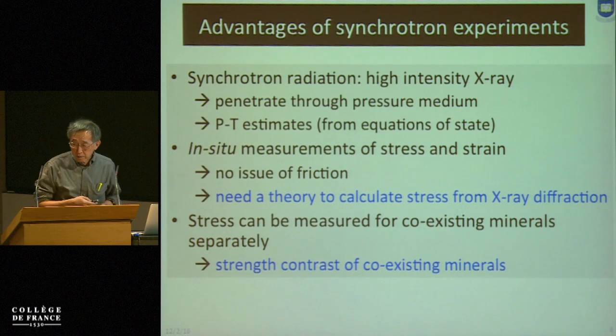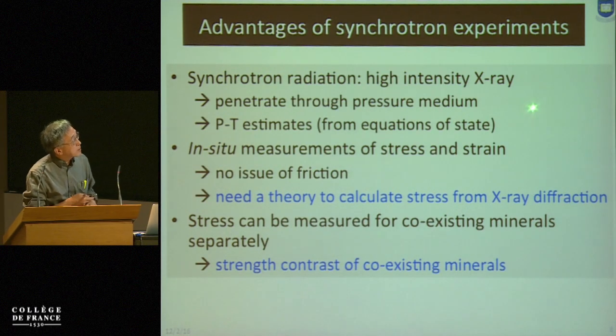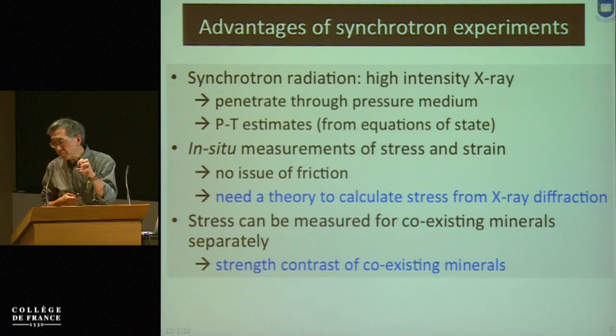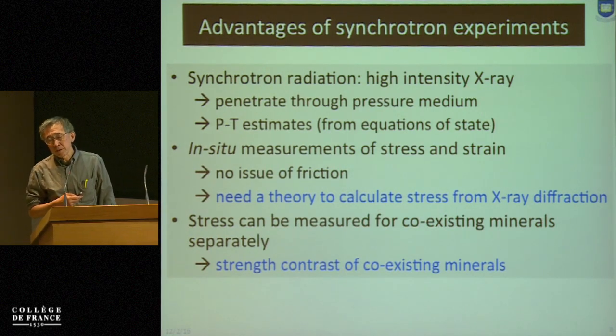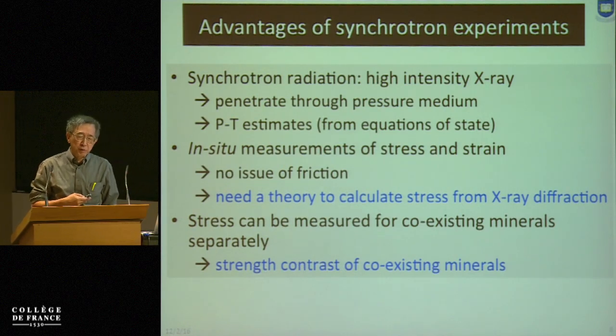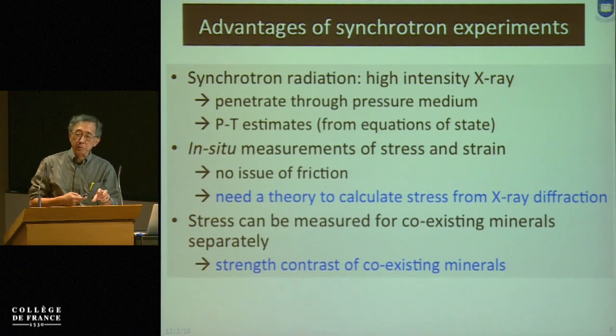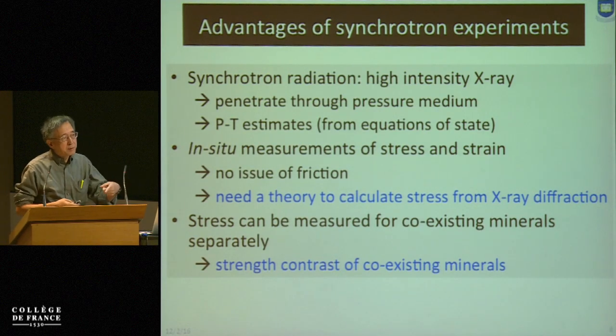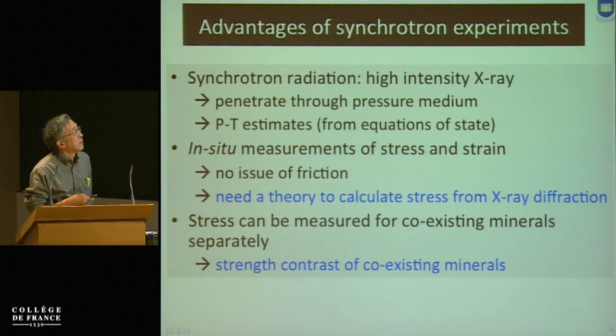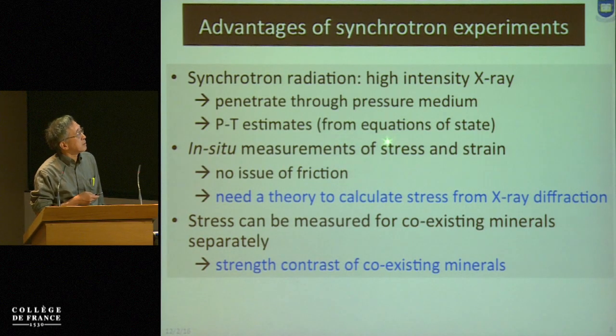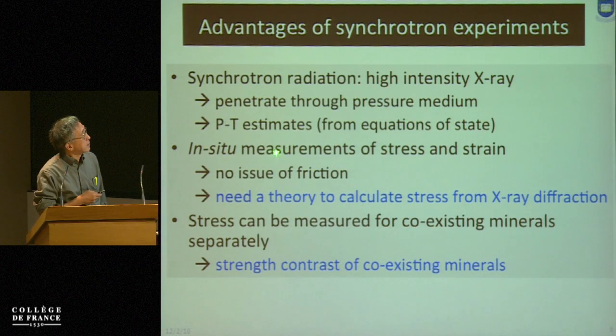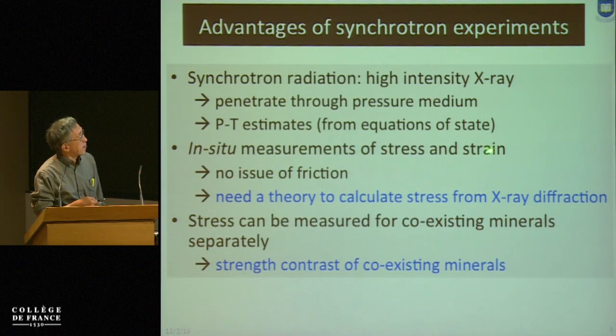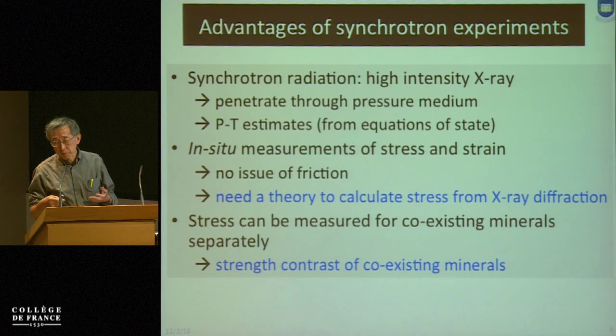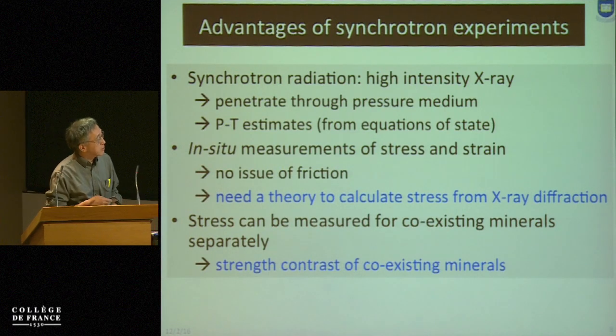X-ray does quite a few things. One is that by X-ray you can measure the volume of your sample, and then using an equation of state you can estimate pressure and temperature in situ, rather than estimating with a thermocouple. You don't need any thermocouple. You just measure the volume, and then you can determine pressure and temperature. And using X-rays, you can estimate both stress and strain. You need some theory to do that, but by X-ray imaging you measure the strain, and by X-ray diffraction you estimate the stress.